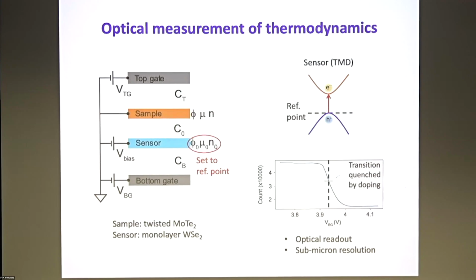So this line is the intensity of the exciton? It's the integrated intensity of the neutral exciton. And once you dope it, that disappears, because that turns into charged exciton. This is absorption rather than emission? This is actually reflection contrast. Yeah, it's a combination of the real and imaginary parts of the optical conductivity.